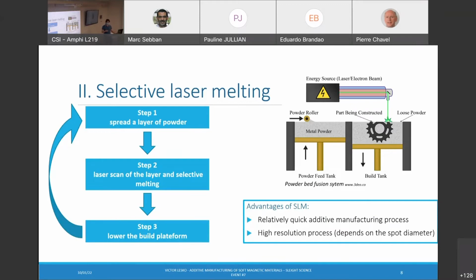The first step consists in spreading one layer of powder. Then the layer is scanned by the laser beam, and the powder is melted selectively. And finally, the build platform is lowered, and another layer of powder is spread, and so on. At the end of the process, the powder which has not been irradiated by the laser beam is not melted, and it is removed, and the part is made from the melted powder. It's a relatively quick additive manufacturing process with a good resolution compared to some mechanical machining, for example.